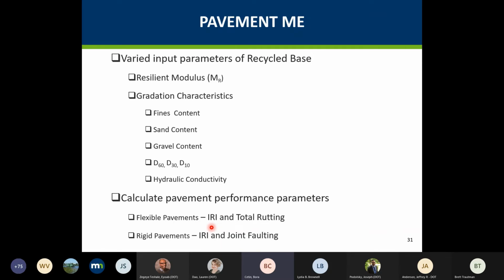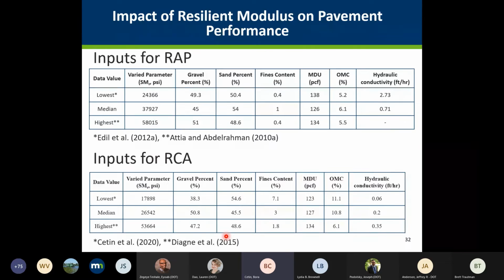In the flexible pavements, since we only vary the recycled base parameters, we thought IRI and total rutting would be the main things that would be impacted. And with rigid pavements, we focus on the IRI and joint faulting. So here is how we look into the impact of resilient modulus on pavement performance. The top table looks into the inputs for RAP, and the bottom table shows inputs for RCA layers. Then we use the median data across the data that we collected. So whatever the median resilient modulus value that we get, we get the median gravel percent that corresponds to this data.